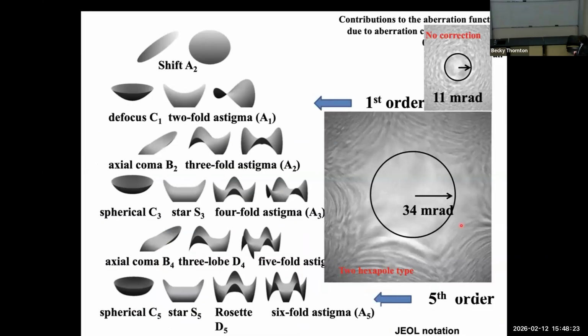Okay, so this is how our corrector works. If you don't have any aberration corrector, maybe it's only 11 milliradians, which is a normal one. But if you have 2 hexapole correctors, you can correct this spherical aberration, which is the 3rd order aberration, so you can get a much wider region. But as you can see in this Ronchigram, you can count 1, 2, 3, 4, 5, 6. This 5th order 6-fold aberration is limiting the resolution. So our next step is to remove this 6-fold astigmatism.